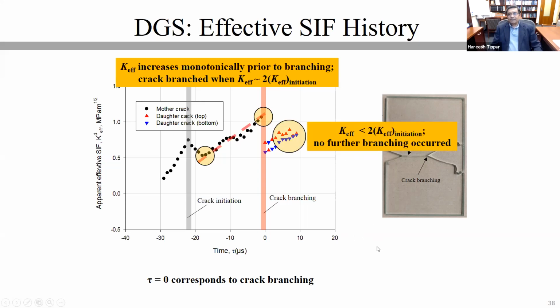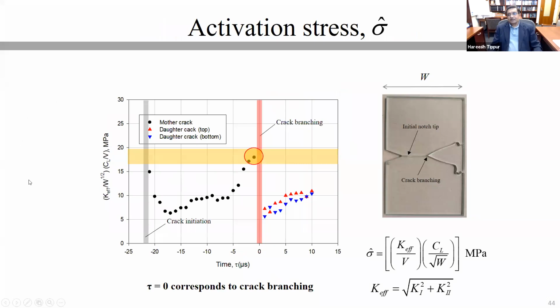Before I show you those results, I want to also bring up the fact that we have a whole bunch of measurements, including the higher order terms. We started throwing these things into groups in order to see what sticks. What I'm going to share with you today in this seminar is that when you combine the effective stress intensity factor and the measured crack velocity in this manner, multiplied with the longitudinal wave speed of the glass and the square root of W, being the width of the specimen, you get a quantity which I call sigma hat here. I call it activation stress for lack of a better explanation at this stage. It has units of megapascals, or units of stress.